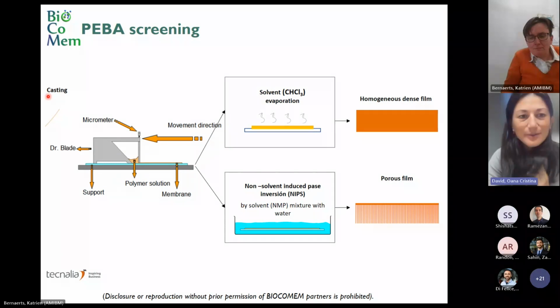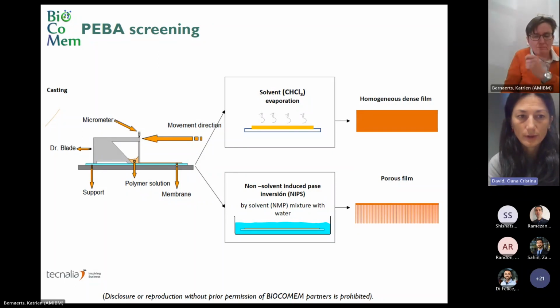So here in this slide, we show how we made this polymer screening. We wanted to see, first of all, the intrinsic gas permeation properties, and also if they have the ability to form an asymmetric structure with a porous substructure. So, can we make a porous film with a top layer that is dense?